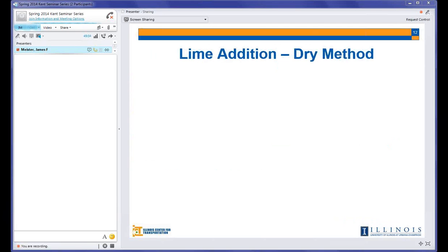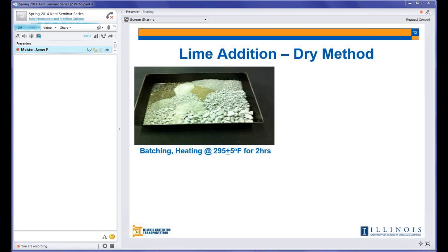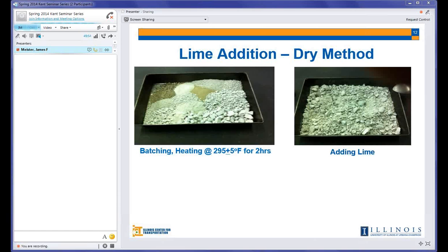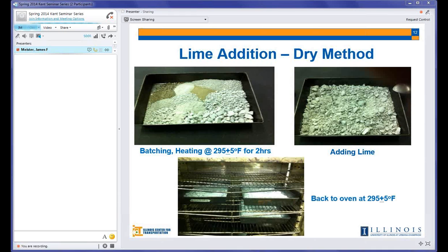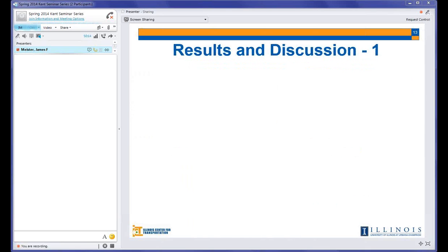Lime addition: there are several addition techniques for lime. In Illinois here we have 3 techniques: slurry, wet, and dry lime. The method that we used in this study was the dry technique, which is basically we batch the aggregate normally, but without the mineral filler, of course, and dry it in the oven for at least 2 hours to make sure that all the moisture is evaporated, at a temperature of 295 Fahrenheit. Then we take it out, add the 1% lime, and after that we add the mineral filler, and put it back in the oven just to make sure that the batch goes back to the mixing temperature. Then we continue with the normal mixing and compaction procedure.